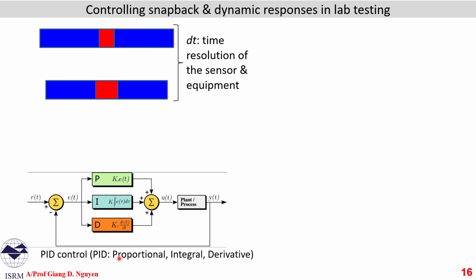So we use this principle in testing to control the fracture process, and the control is based on PID, which stands for proportional, integral, and derivative. Say if we are using the expansion of the red zone to control the process, it means the rate of crack opening should follow the specified value that is used to control the fracture process.